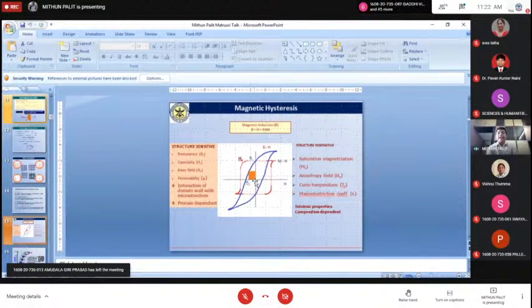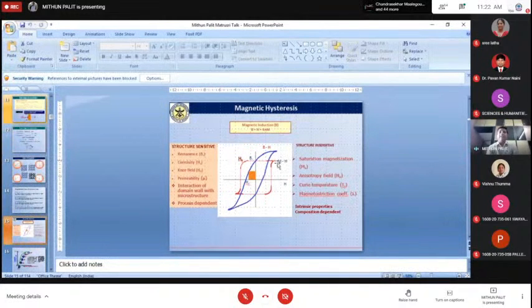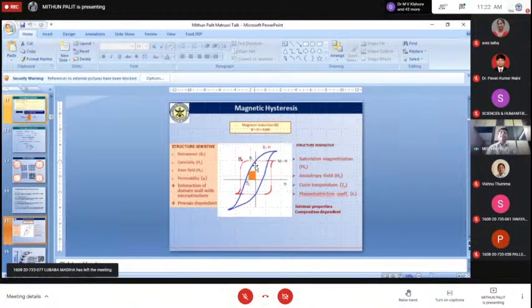If we are at the origin, that means we have not applied any magnetic field. Thereafter, when the magnetic field is applied, please refer to the red color loop, the square shaped loop. When we keep on applying the field, after some field there will not be any further increase of magnetization of the material, because all the domains of the material will be oriented or saturated by then. And then on reversal of the magnetic field, the magnetization will keep decreasing, and even when the field is zero, it will still retain some amount of magnetization, which is called remnant magnetization.